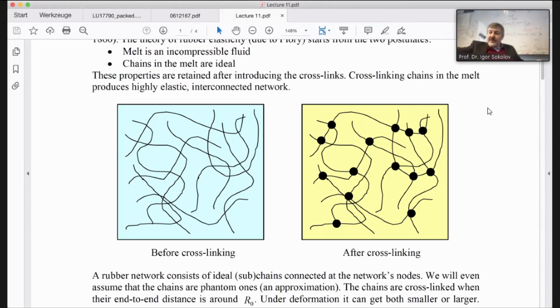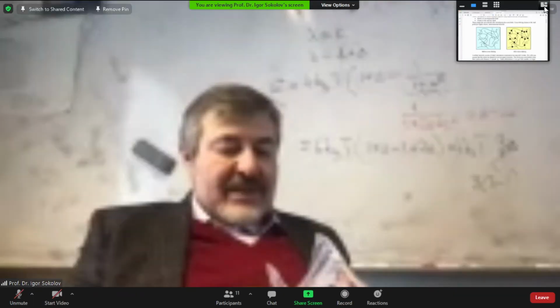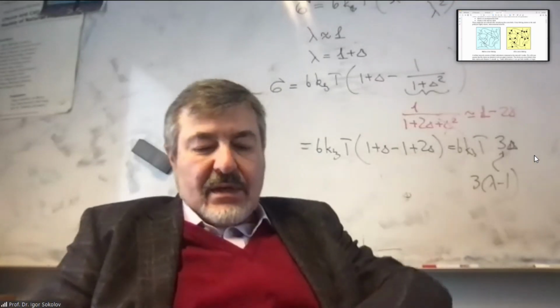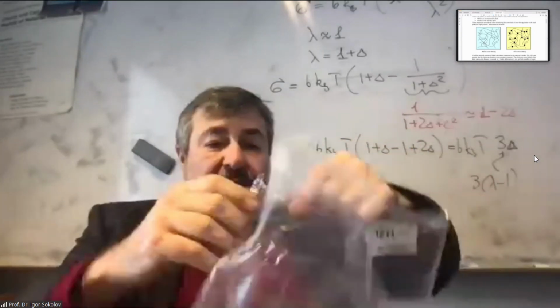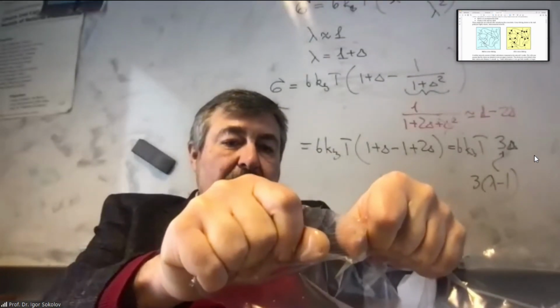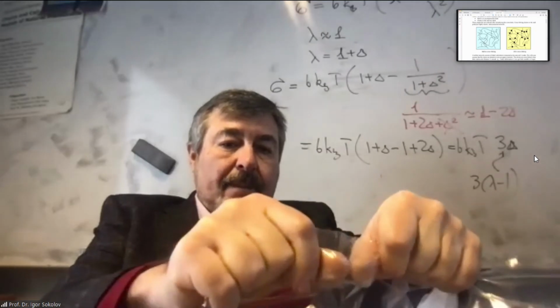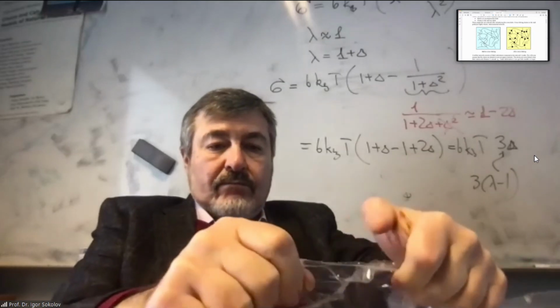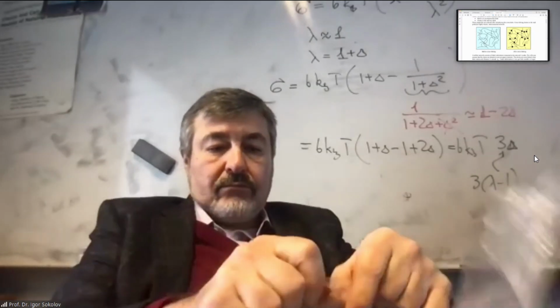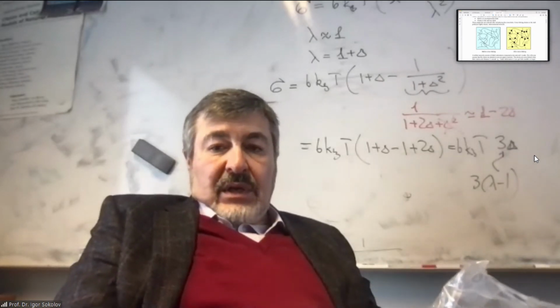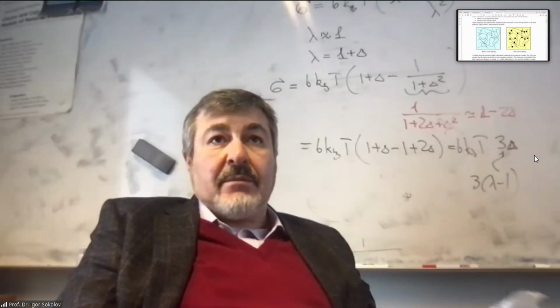I have here another bag. Now it's a different plastic. It's quite a thick polyethylene. So there are no cross-linkers here. And I pull. I pull slowly, but steadily. What happens here? We get an irreversible deformation. You get an irreversible deformation, this is true.